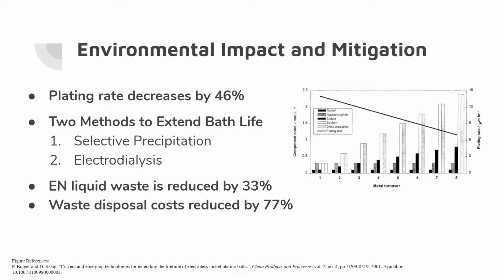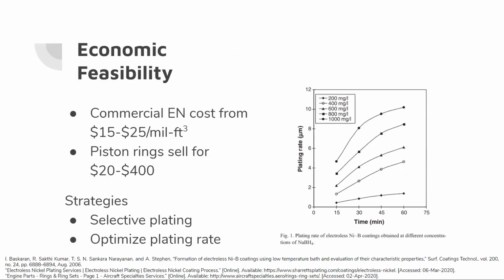In comparison to the conventional processes of chromium plating, it approximately consumes 3,000 liters of water and produces approximately 75 kilograms of hazardous waste. With this treatment, we could reduce waste by 33% and minimize disposal costs by 77%, as the bath can be recycled up to 12 times in the manufacturing process. And now Linda will discuss the cost analysis.